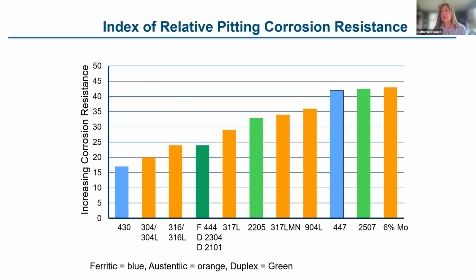So I'm showing a range of stainless steels on this graph. The least corrosion resistant have the lowest bar. Everything in blue is a ferritic. Everything in orange is an austenitic. The duplexes are green. This shows that you can get a wide range of levels of corrosion resistance in any alloy family. The 304 and 316 that are most commonly used in architecture and other applications are at the low end of the scale. If you have a more corrosive location, increasingly 2205 is commonly being used, and you can see it's in the middle.